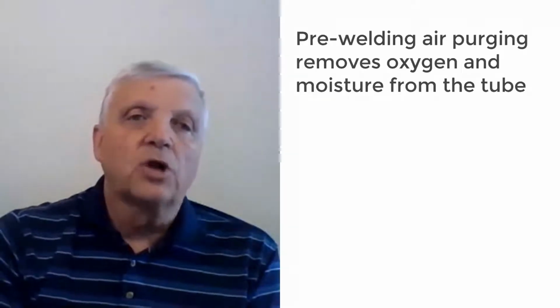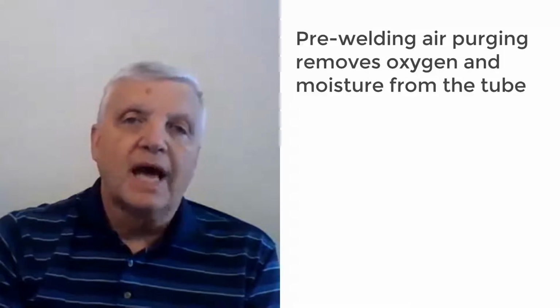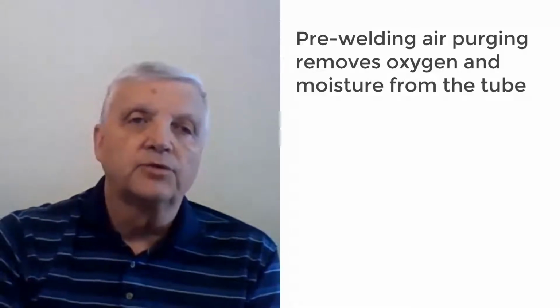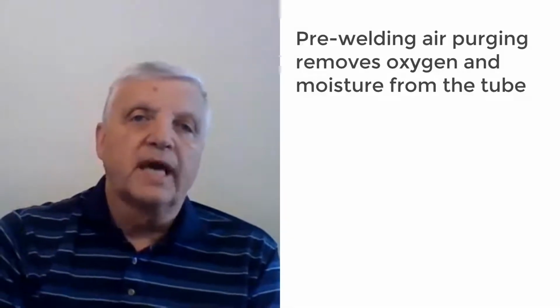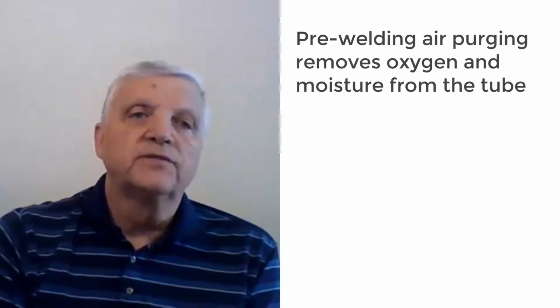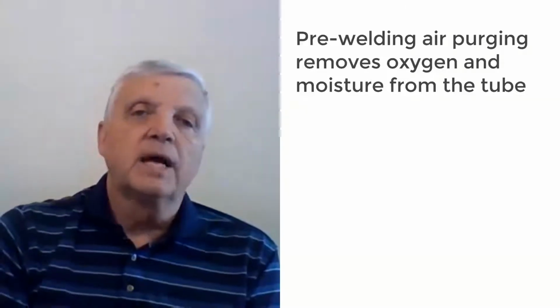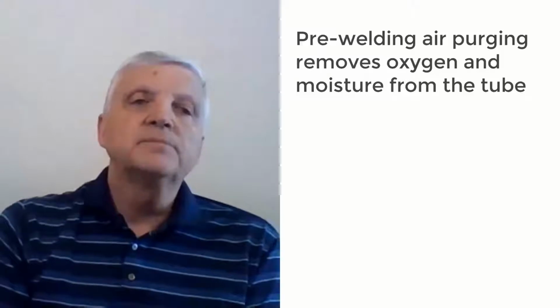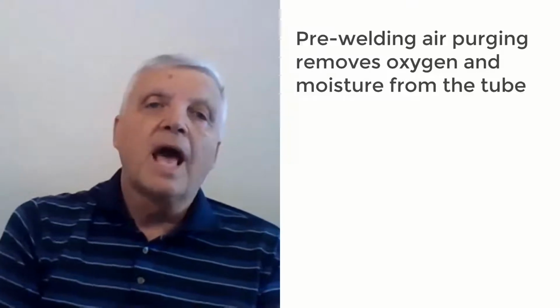Before the weld can be started, a sufficient purge time must elapse, allowing the gas to remove air from the tube. Even moisture present in the gas can contribute to the creation of discoloration, and thus the supply lines providing the inert gas must be leak-free to prevent drawing in air and moisture from the surroundings.